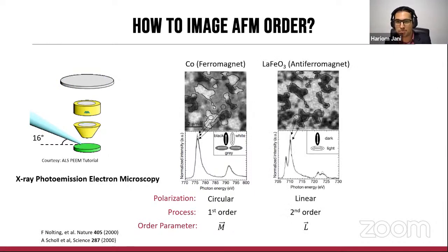Whereas for an antiferromagnetic system, we now look at a linear polarized X-ray dichroism. And this is a second order process, slightly weaker as compared to the first one. And here we can map the Néel order. This is necessary because the antiferromagnets have almost negligible or absent net magnetization, and therefore we would usually not observe circular dichroism in these systems. As noted in these images here, one key point to observe is that maximal contrast in the ferromagnetic case is between oppositely aligned textures, but in the antiferromagnetic case, it is not possible to distinguish 180 separated domains, but only 90-degree separated domains, and that is why the contrast looks like this.